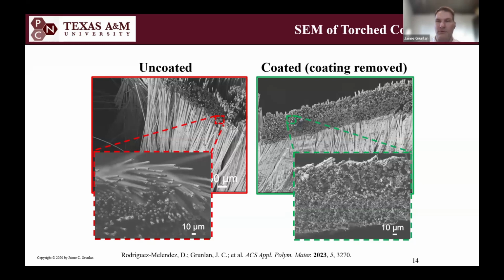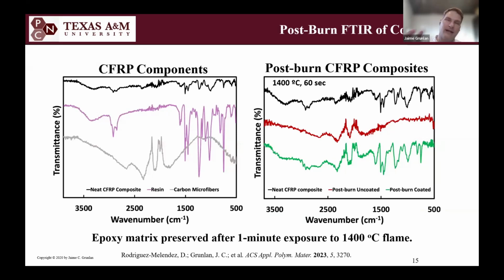But yeah, you can see here that we've protected the epoxy that's holding the carbon fibers together with that coating. And FTIR can be used to prove that the epoxy is still there in the coated composite while it appears to be gone in the uncoated.